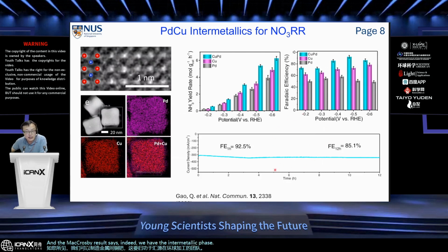And if you do the catalytic reaction, we can get something more active than the monometallic counterparts, copper and palladium. And they are also quite stable as well. So this is very good. But we have a problem, right?